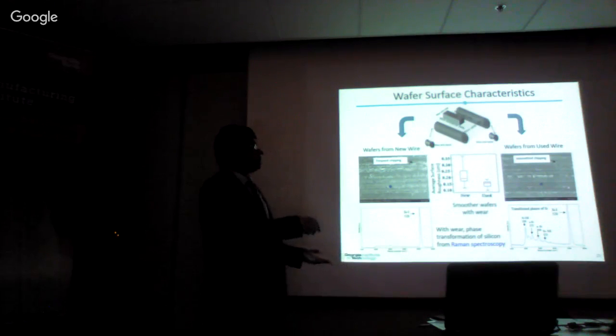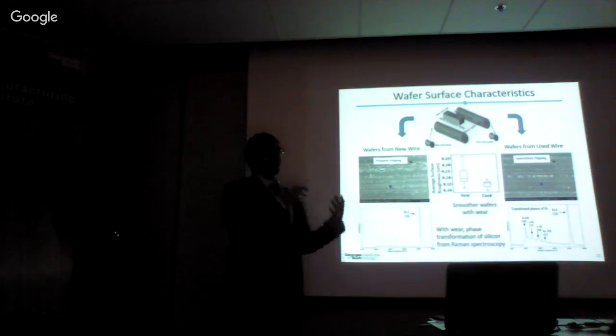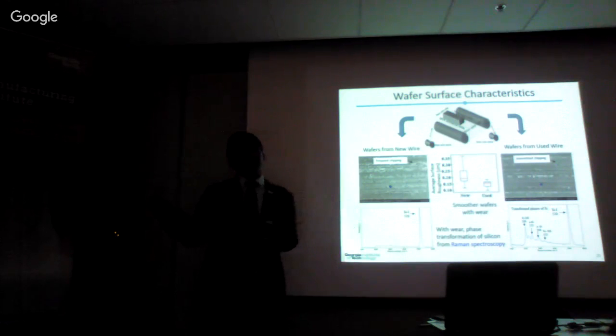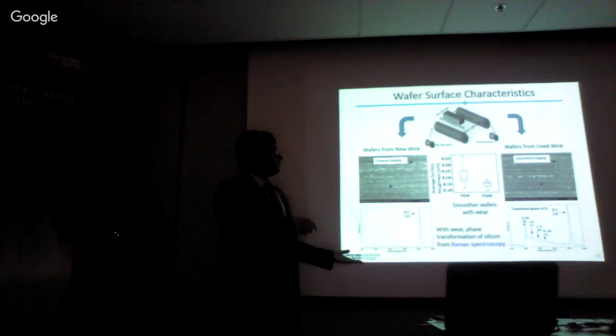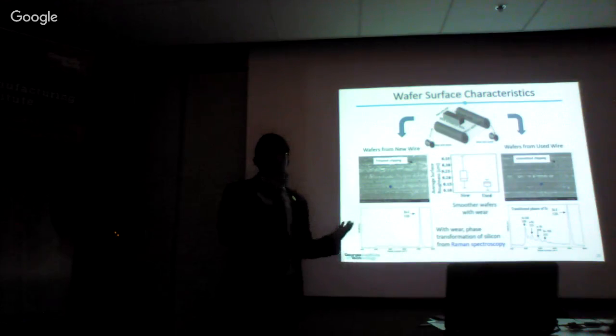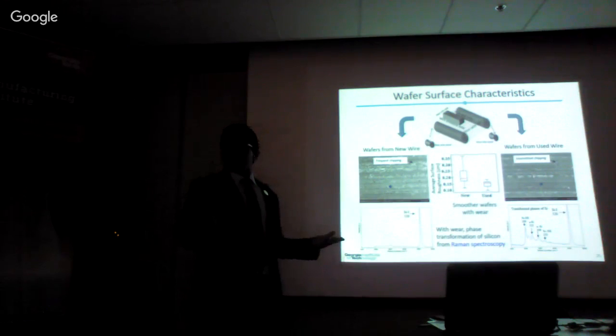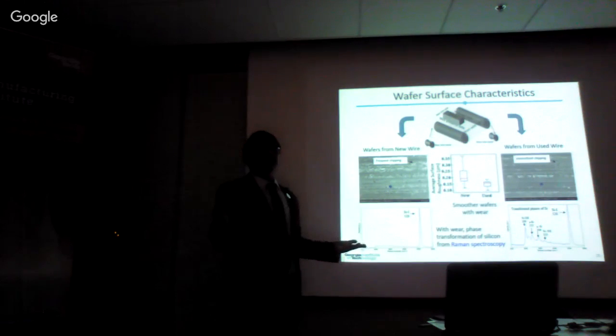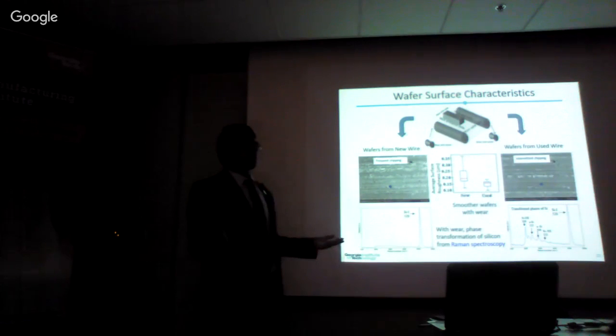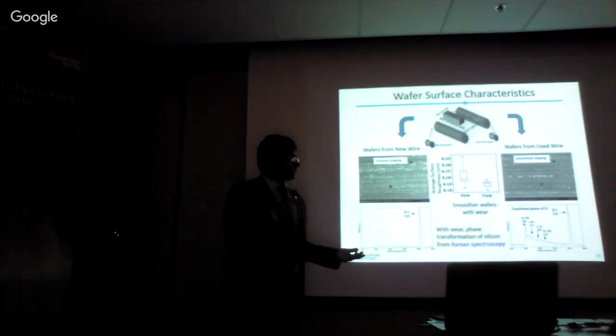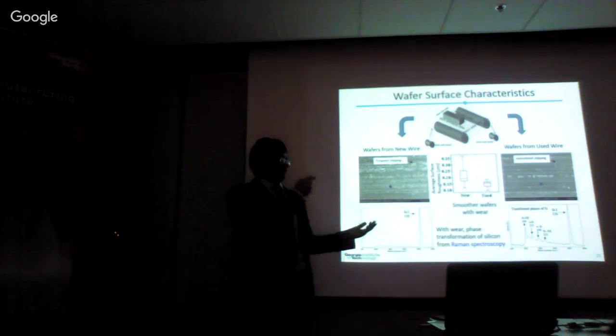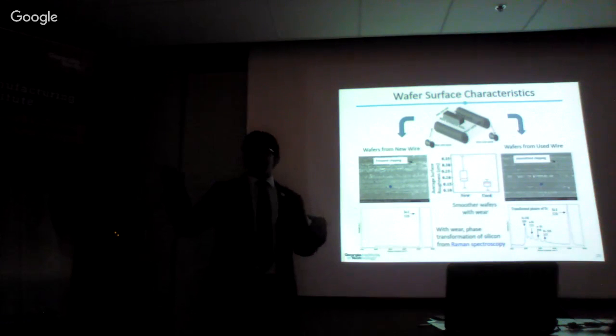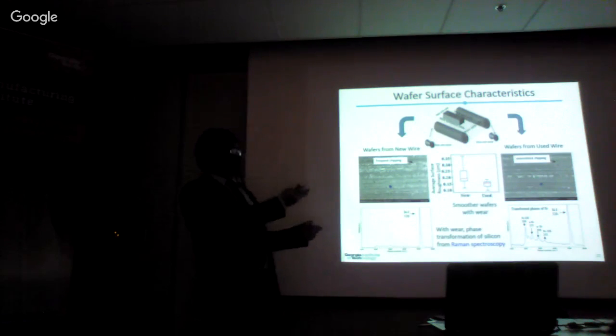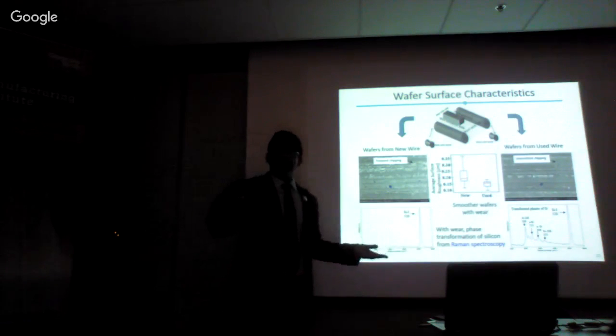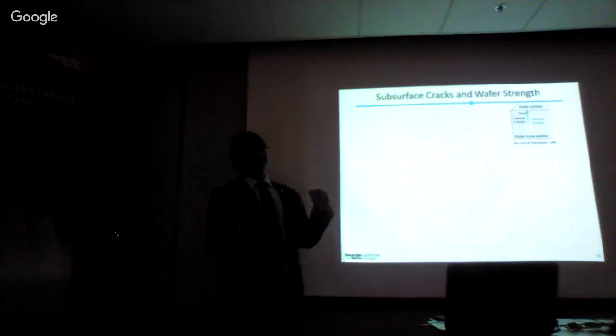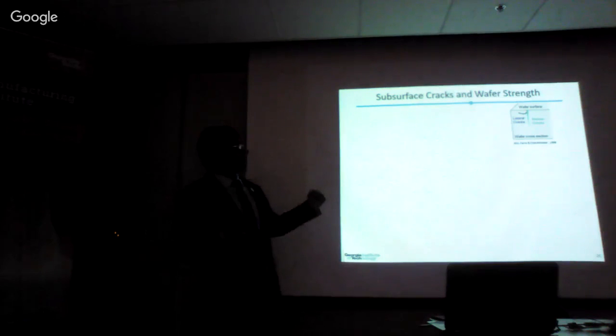And that's what we see even on the surface, that the wafers cut from the used wire side have a more ductile surface. So silicon is being removed like butter, without much brittle material removal taking place. So you might say, oh, this is great. With used wire, we have better wafers with a smoother surface. This is what we want. We have reduced microcracks. But there is a twist in the tail, which is the subsurface cracks.